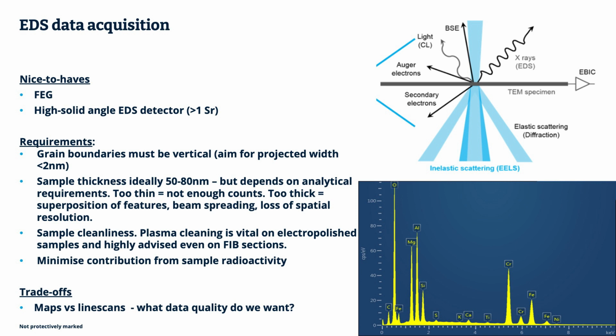Sample cleanliness is a bit of a touchy subject. With electropolished samples, it's essential to plasma clean them to get rid of any hydrocarbon contamination on the surface, because that will migrate to the beam and just result in a filthy black mess that you can't see through. Samples can be too clean though, and if they're extremely clean, you end up just drilling holes in them when you keep the beam stationary on the sample for too long.